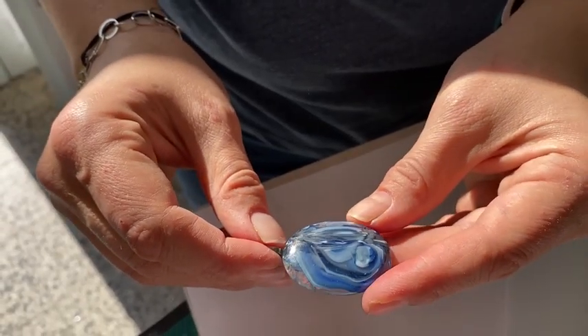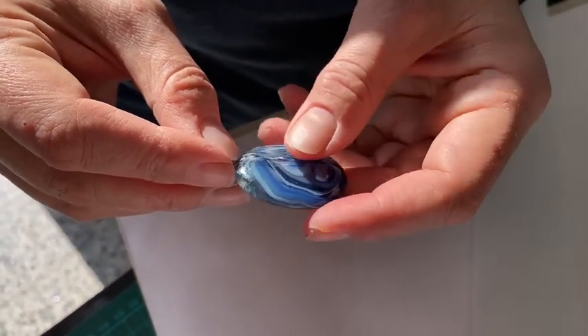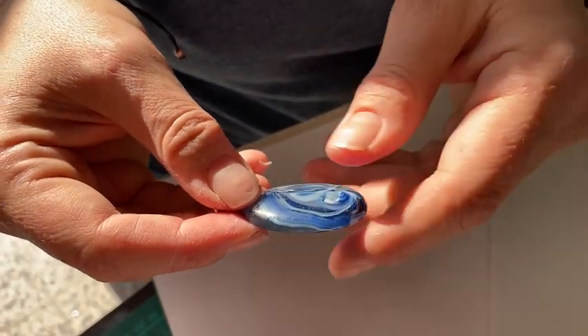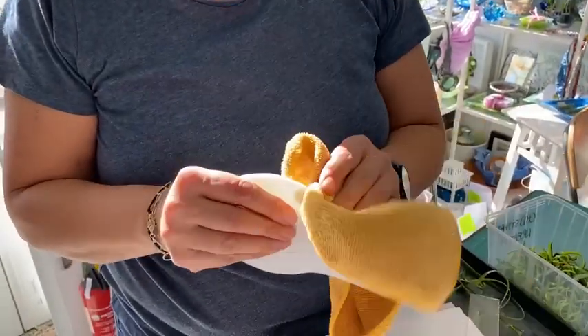Let's have a quick chat about devitrification because I like to give a bit more information sometimes. Devitrification is basically when the glass looks a bit scuzzy — cloudy and dull. On this piece you can hopefully see it. You can even get fingerprint marks from the grease on your fingers that can make your glass devitrify. The only way to get rid of it once it's there is to either sandblast a layer off or put a new layer of glass on top, such as glass powder — but it's much easier just to clean your glass properly. Also, if you're grinding the edge and don't take it down to a 400-grit grind, you'll likely get devitrification at the edge. So give it a really good clean.